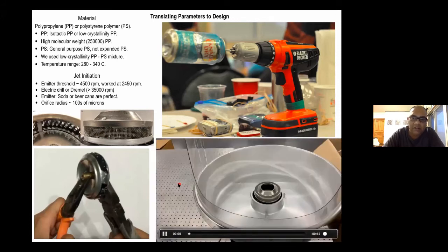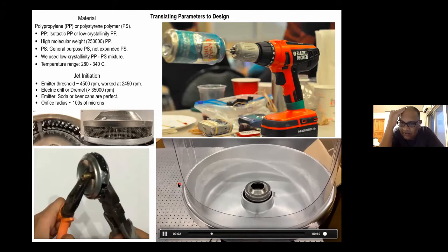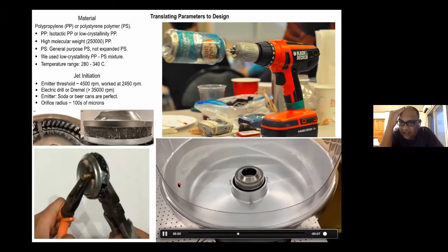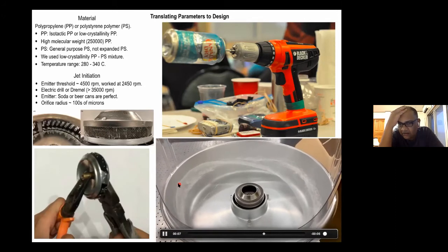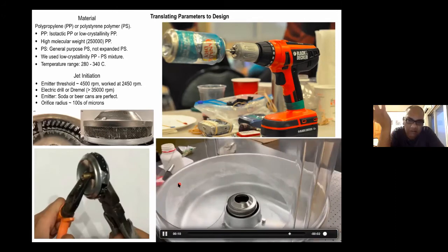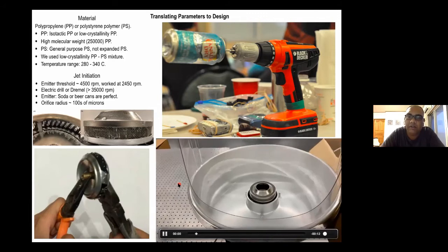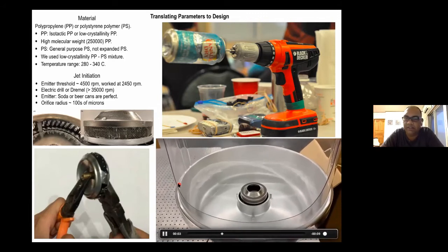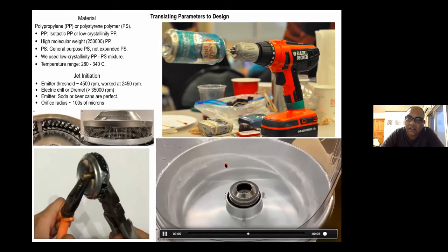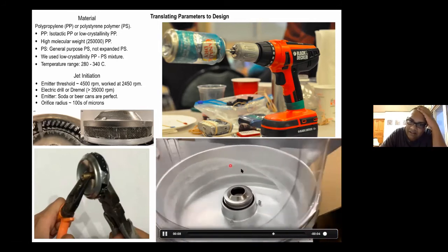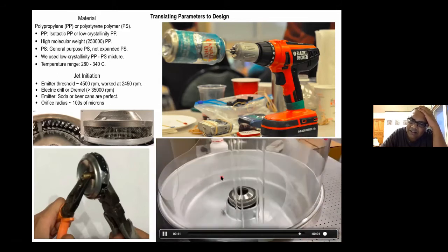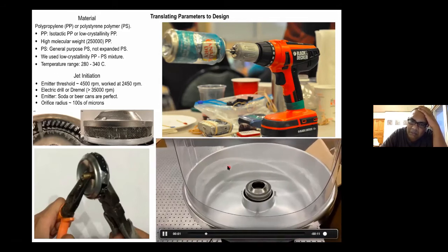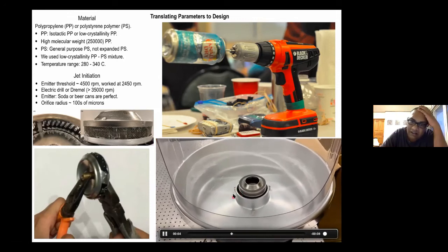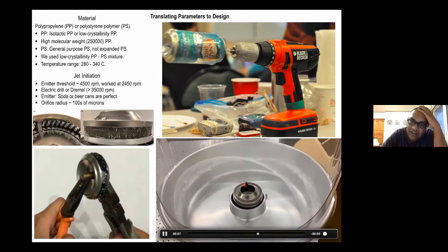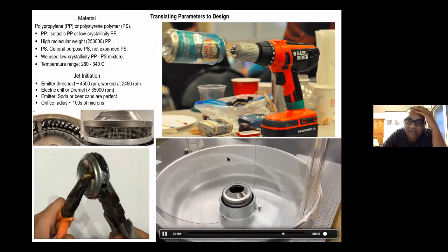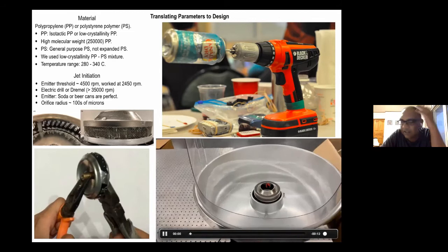So it was very simple. Most of these commercial machines are either electrically heated or gas heated. Either one works. All you need is to melt the polymer to a high enough temperature, and then you're in business, and you get this. Getting these fibers itself was very easy. There was nothing special at all in doing that. But tweaking the orifice radius and other parameters to get fibers of the right diameter took a lot of the tinkering effort.